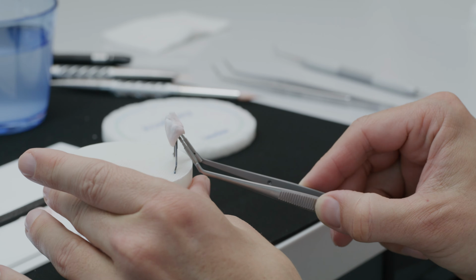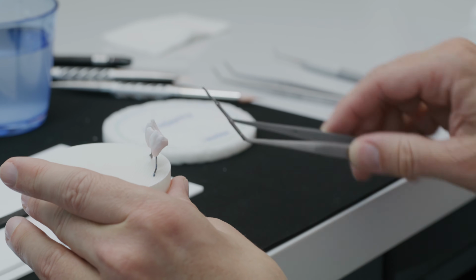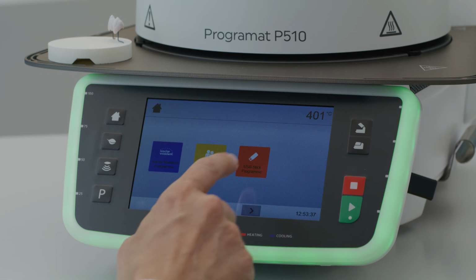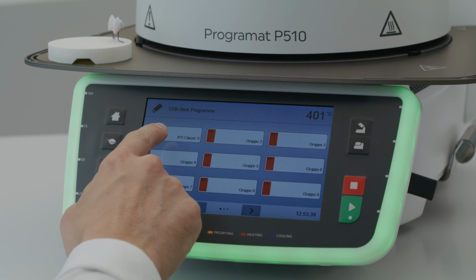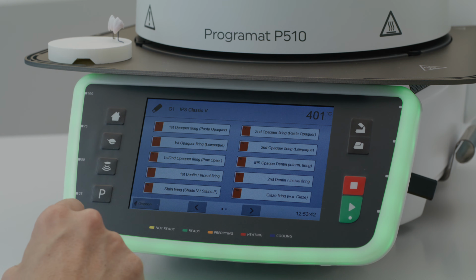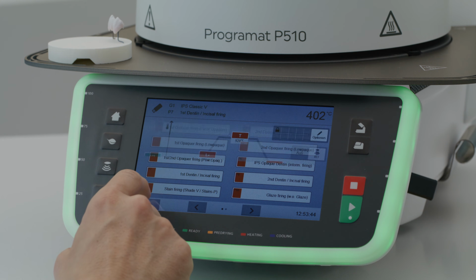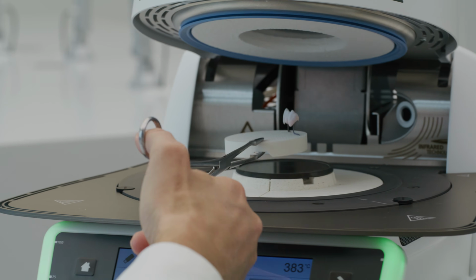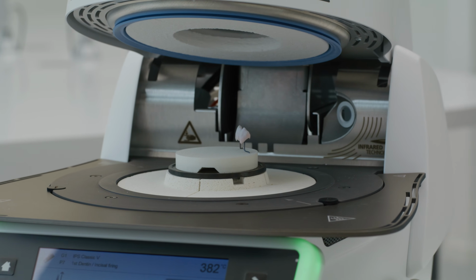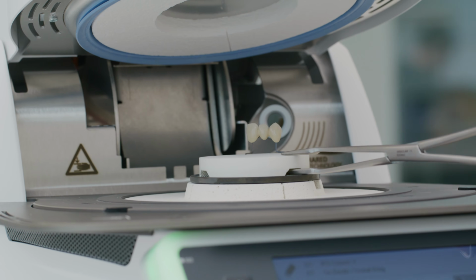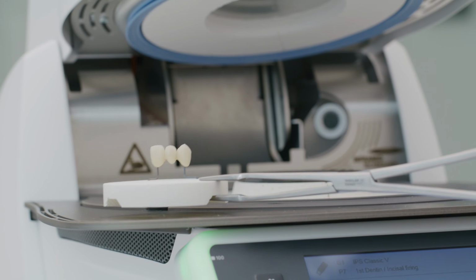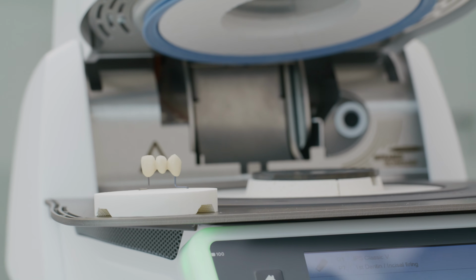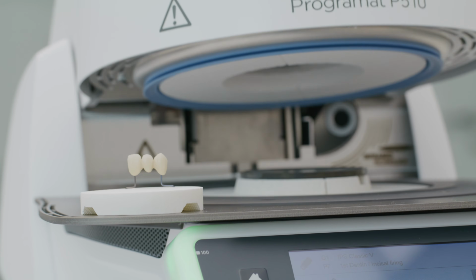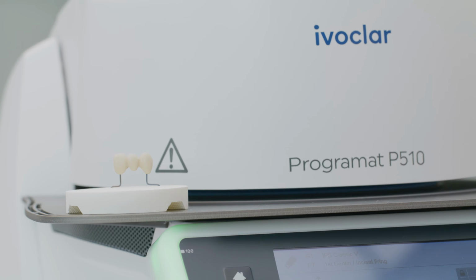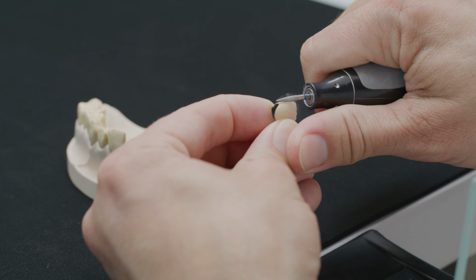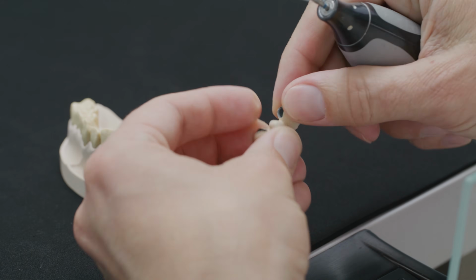Place the completely layered restoration on the firing tray and ensure adequate support. Now it's time for the first dentin and incisal firing. It's essential that you observe the firing parameters recommended by Ivoclar and pay attention to the standby temperature of 403 degrees Celsius. Remove the firing tray from the firing chamber only once the furnace head is completely open and the acoustic signal has sounded. Allow the restoration to cool to room temperature. Then finish it and subsequently clean it with the steam jet.